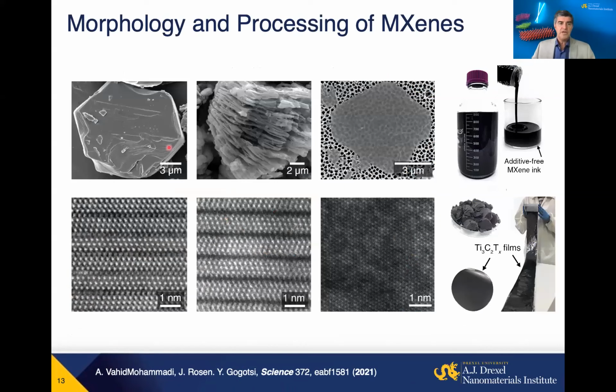So if you look structurally at the initial MXene precursors, you see these layers, in this example of titanium carbide Ti3C2. Those three brightest layers of spots are titanium atoms you can see in the structure, and you can see aluminum in between the layers. After etching, we get particles of ceramic looking like basically thermally expanded graphite or vermiculite clay. You see the intermediate layer disappeared, replaced by surface termination, and these more faint dots appear on the surface. And after delamination, which we can do by intercalation, for example, or sometimes without, depending on the method of synthesis, we get these sheets, and this is a single layer. In this case, probably like 6-7 microns in size. Here we can make up to 20-30 micron flakes now.